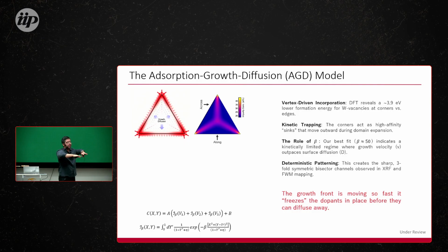I'm not saying that there is no vanadium along the other homogeneous samples, all right? I'm just saying that most of the concentration of the vanadium atoms, because of this competition, because the sample grows so fast, the growth is much faster than the diffusion of the vanadium, which takes a little bit more time, so the concentration is there. That's what we are proposing here.